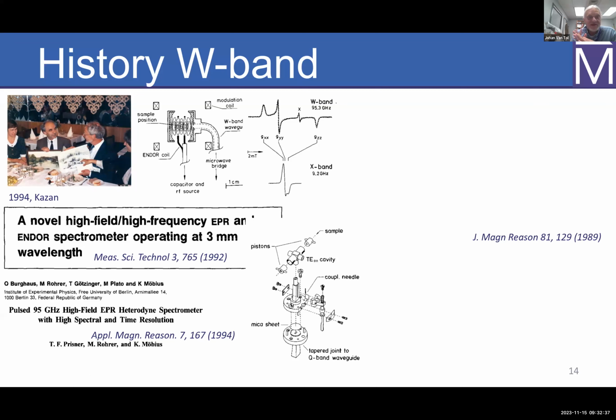In Berlin, they started to really build a very capable high field, high frequency spectrometer at 3 millimeters, so that is W-band, where they employed both the Fabry-Perot type resonator, but also a TE01 resonator, and started doing pulsed quite quickly as well. And you see some of the earlier results. This is actually a manganese line that they used as a reference. Also over quinone, I think, in this case. So that was really the start of quite an instrument development.